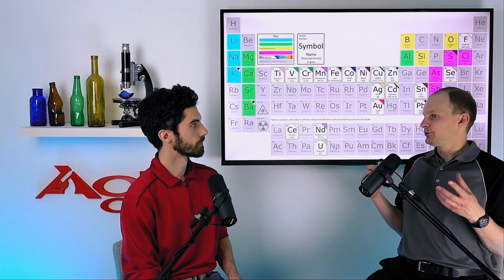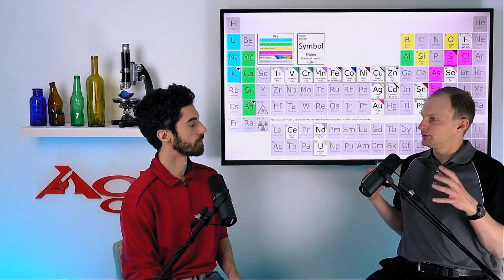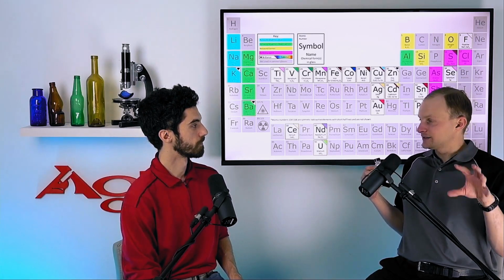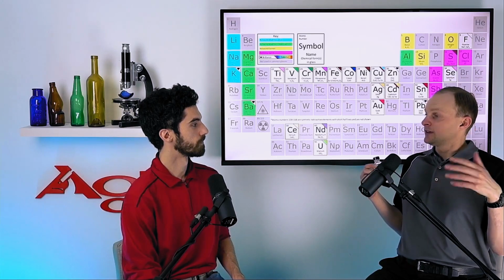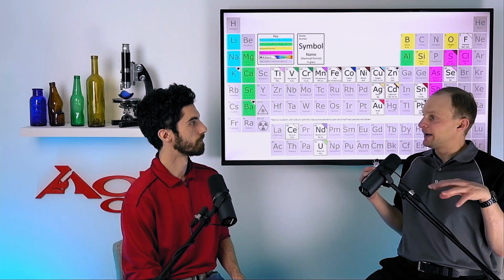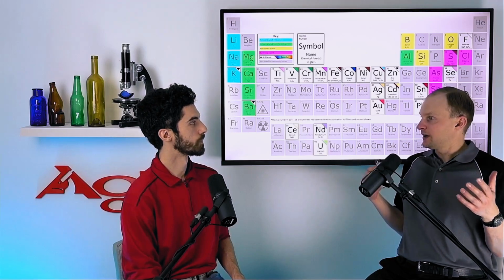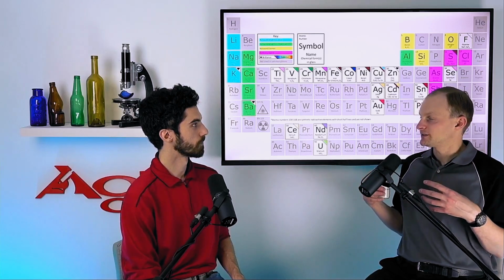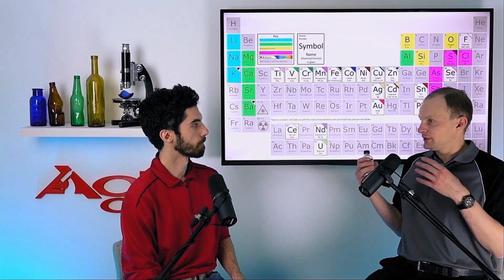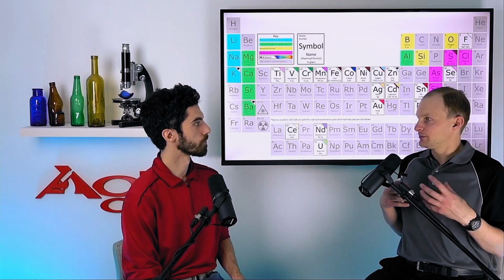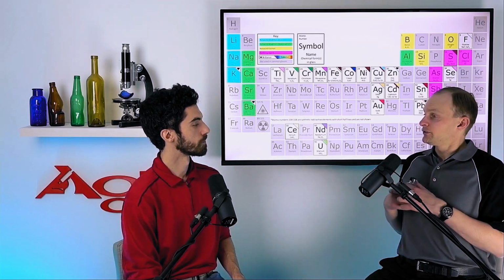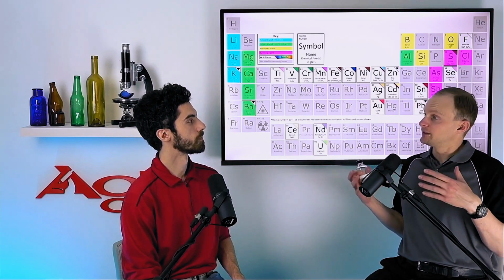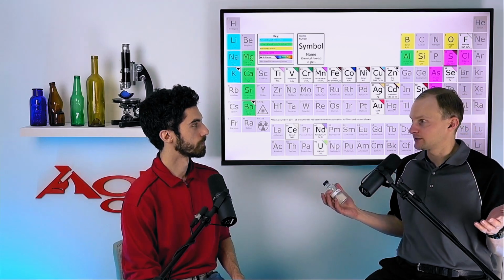And some of those minerals don't dissolve very well. They're little particles of what we call refractory heavy minerals, and they are not going to dissolve and will come out in your glass as defects. You can also have excessive amounts of iron impurities. Iron's a very common contaminant in sand, and that iron will cause increased coloration of the glass, typically a greenish or yellowy color, depending on the oxidation state of the iron. So to have clearer glass, we need higher purity levels of sand, and different deposits have different levels of purity and hence different costs.